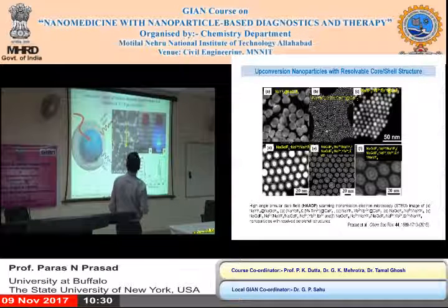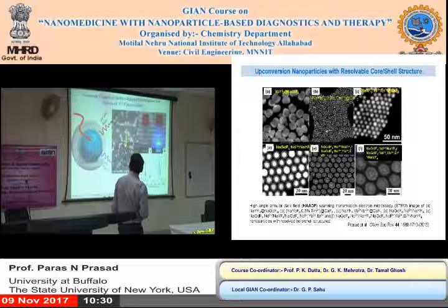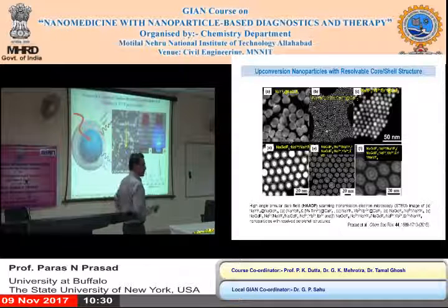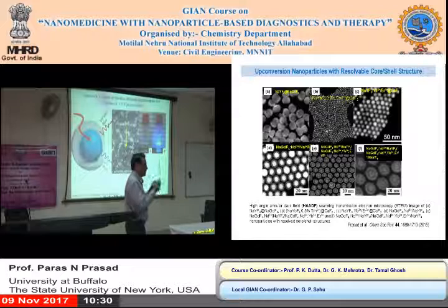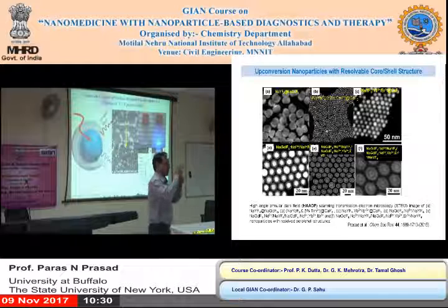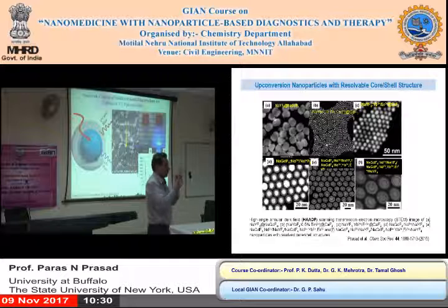So anyway, this gives you an example of putting the shell on. Here the core is this, and then you form a shell on that of just calcium fluoride on the top. In this core shell structure, you minimize surface deactivation, and if there is no rapid relaxation, they can climb up more ladders. They don't relax very fast and dump energy, because the surface is protected.